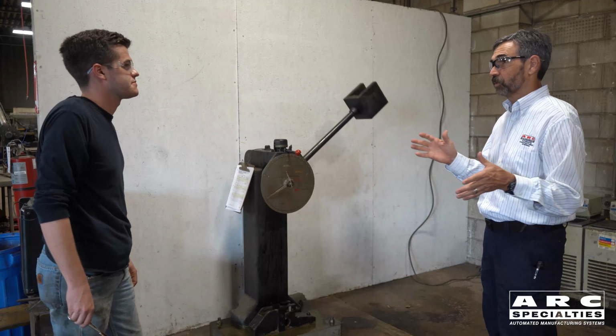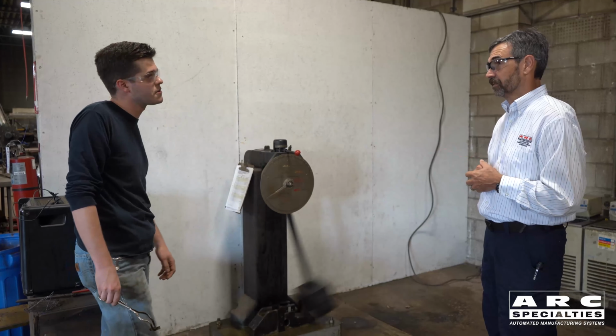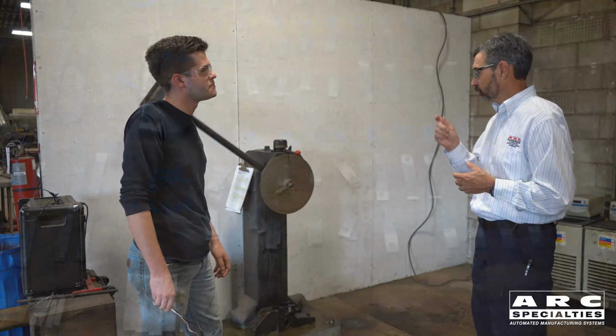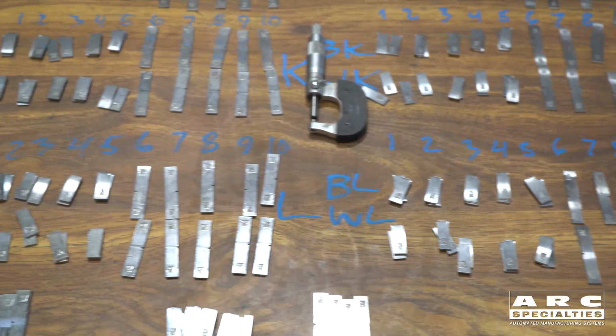Ten foot-pounds, that's low, right? That is kind of low, but they are also sub-sized specimens. So these are not the normal, what's the normal dimension, 10 millimeter? 10 millimeter by 10 millimeter. And these are thinner, why? Well, the pipe thickness just doesn't allow for a full-size bar.